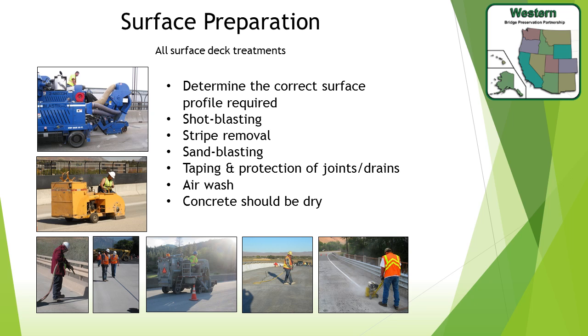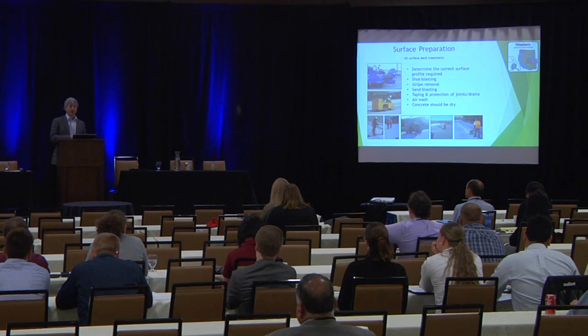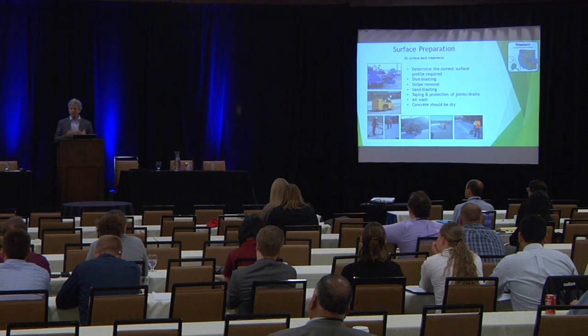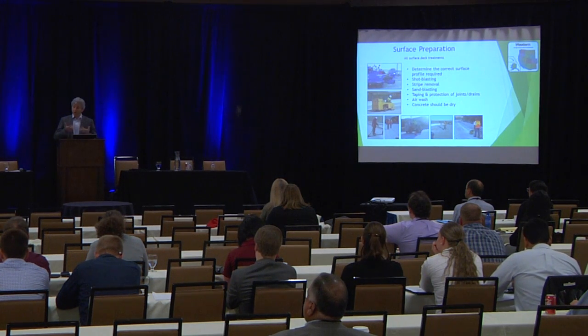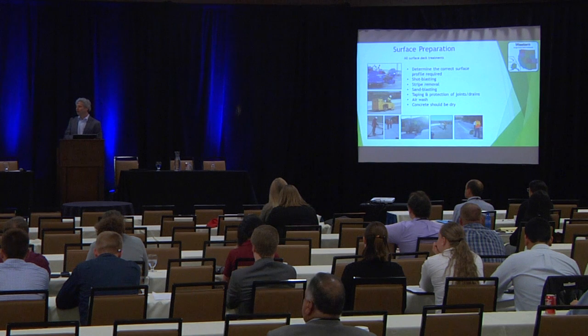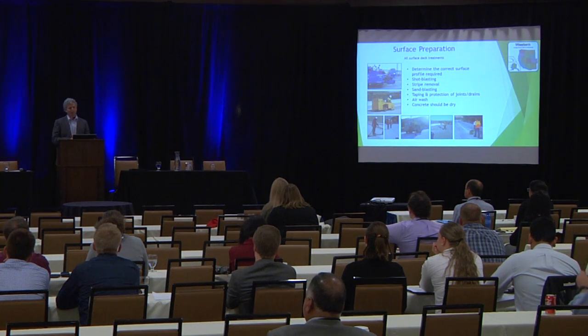I'll go back to an example from years ago here in Utah when I was involved with one of the first overlays. The tech rep called and said there was some kind of whiteness on the deck. I showed up, poured water on the deck concrete — it made the concrete darker and you could see a lot of curing compound on the deck. What was left was in the pore structure, which is where the polymer resin binder goes to get good mechanical interlocking into the deck itself. We called the shot blast contractor back, and his comment was, 'This is the way we always do it.' That was not a good answer.